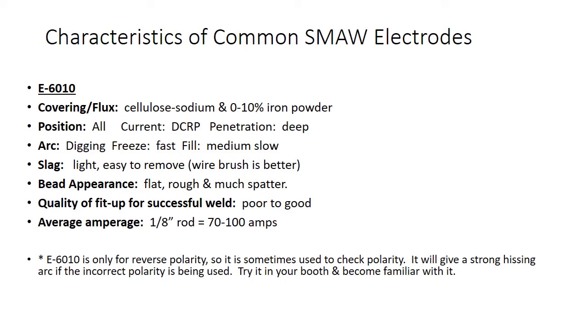You can have a really poor fit up, and if the welder knows what he's doing, you can have some successful welds. And it gives you the amperage there for a 1/8 inch rod, 70 to 100 amps. Not a bad electrode, but it's got its place. Some people don't like to run it because there's a lot of fire involved, but actually it's one of my favorites.